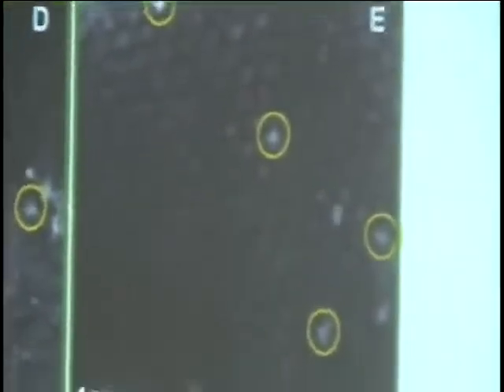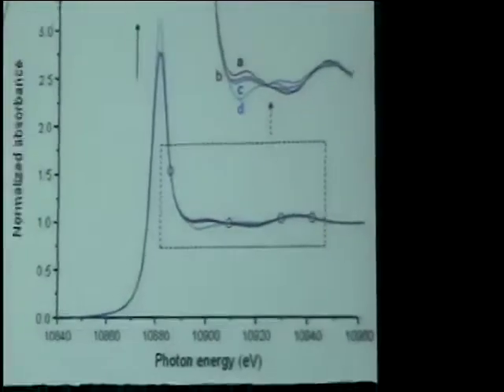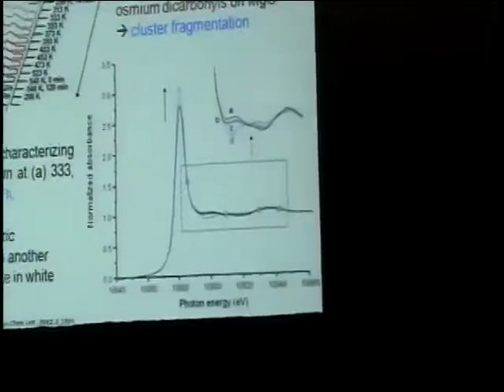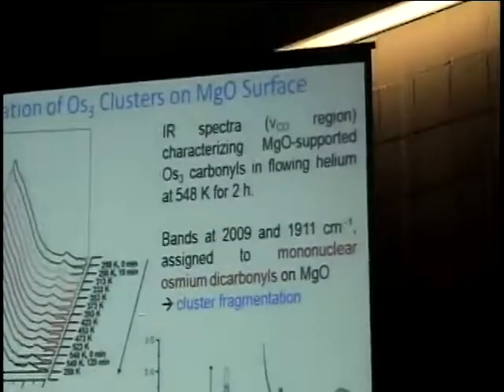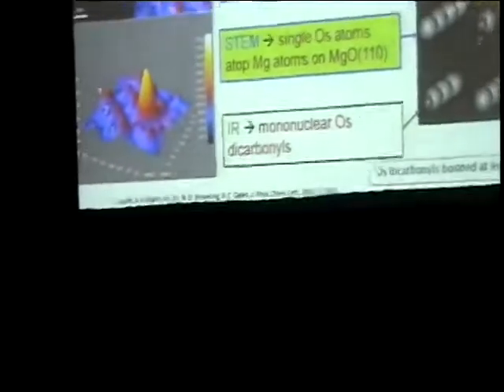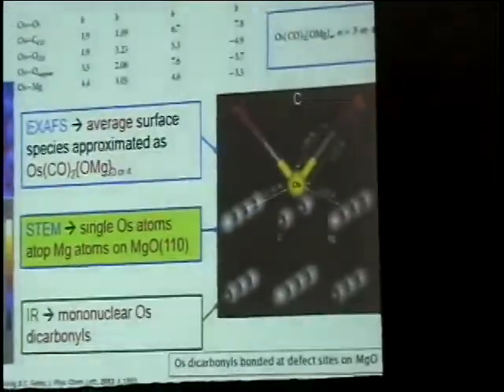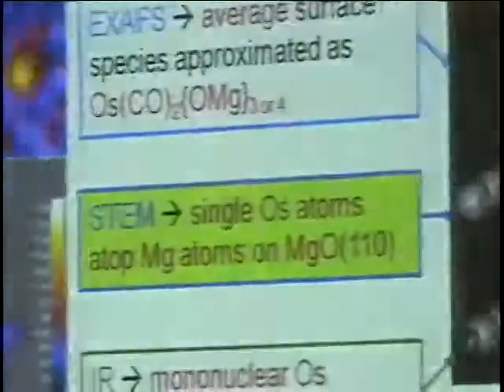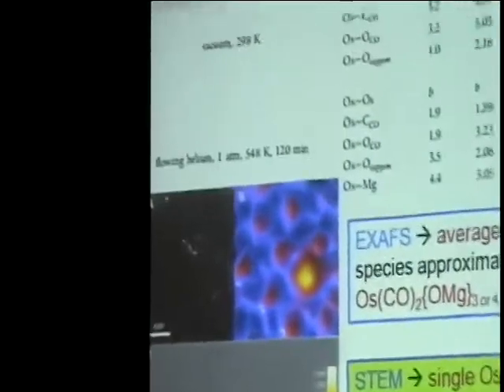We can characterize that well. So here are a few spectra. If we start with the triosmium and we go to the mononuclear osmium and look at the XANES, we see the isosbestic points that say we're doing that conversion in a stoichiometrically simple way. So it's a sharp synthesis. And we do infrared, and it bolsters what I'm saying, so we get osmium dicarbonyls. So we have a simple sample to work with, and we can push the microscopy to learn something important about the structure, not just of the metal species, but of the metal-support interface. So we think that's an important part of what the microscopy is bringing to catalyst characterization these days.